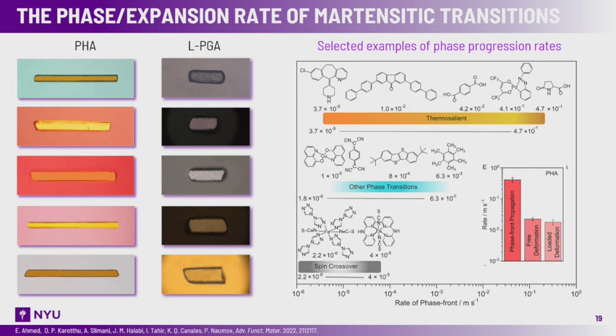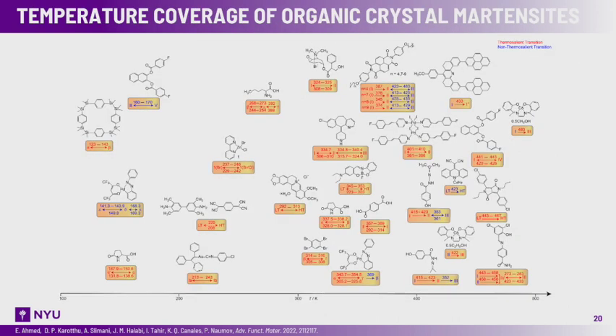Of course, in this case we have to use high-speed recording because these are very fast processes, in order to track how the phase transition progresses throughout the crystal. But we also found that the actual expansion of the material is one order of magnitude slower than the progression of the phase front. The reason for this is that some energy is dissipated from the crystal, and there is some kind of resistance of the crystal to this process.